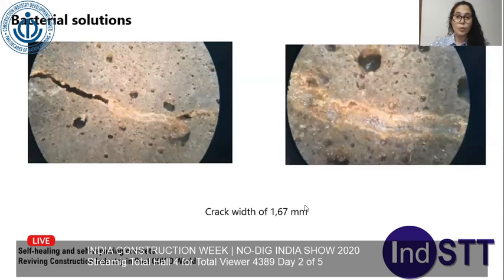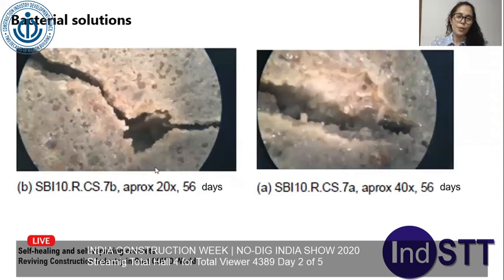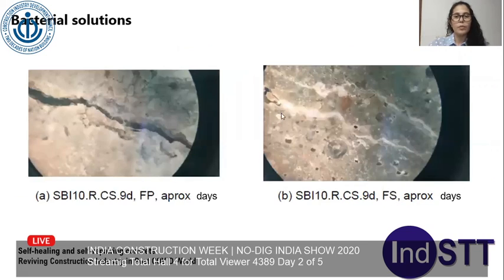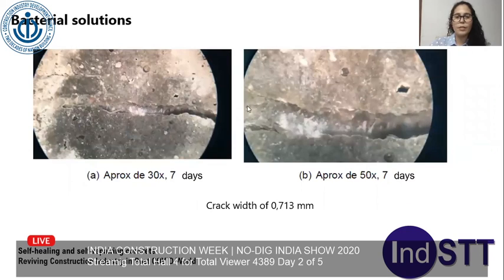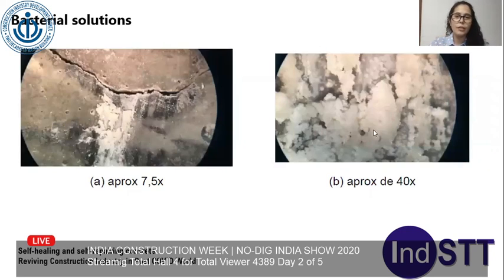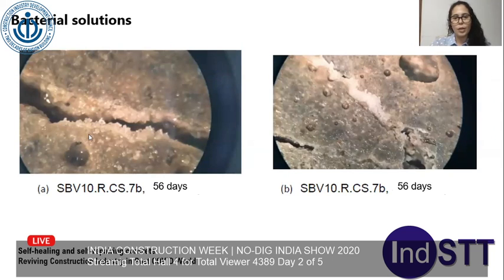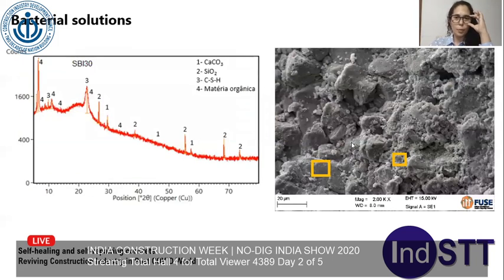From bacterial solutions, we have the crack completely healed with 1.67 millimeters, sorry. And we also have here inside the crack continuous healing from small cracking and bigger cracking. And here inside the crack there's a solid material in all the continuous crack. And here there's a common occurrence that material is not only inside the crack, but also on the surface of the samples. Also, we can check those phenomena. And here we find calcium carbonate, silicon oxide, CSH, and organic matter.